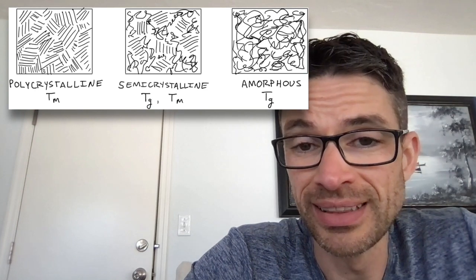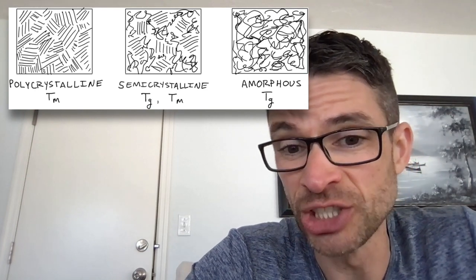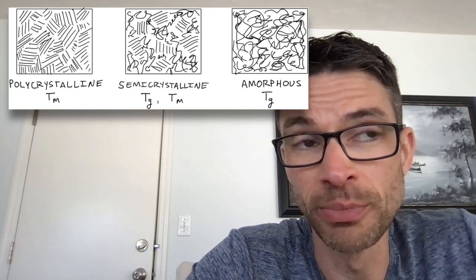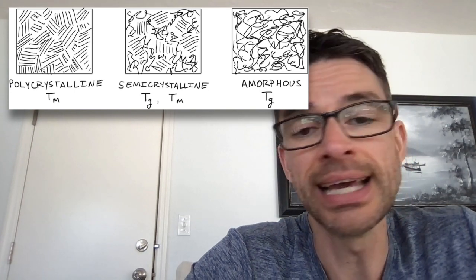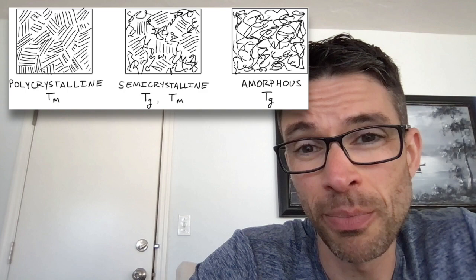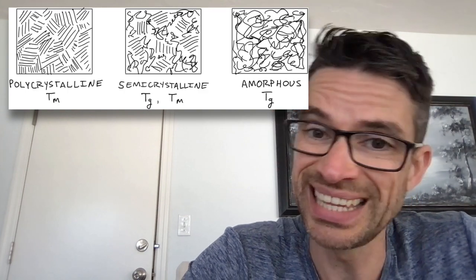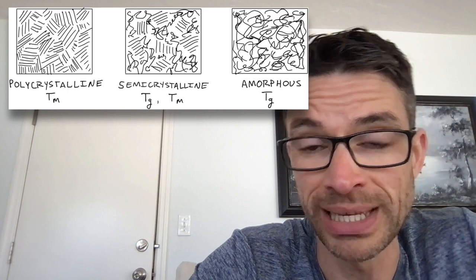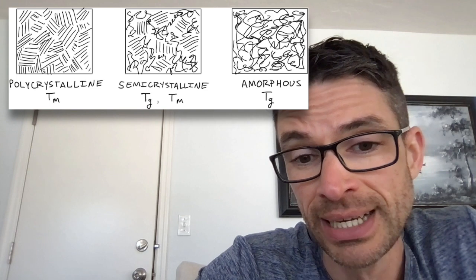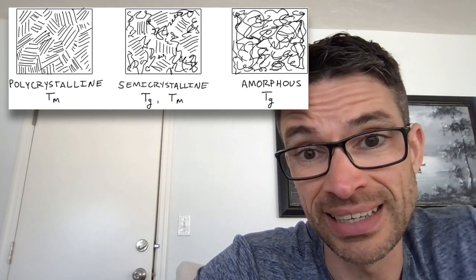The semi-crystalline sample thus has both a TM and a TG. Above the TG, the material becomes more elastic, and above the TM, the material is melt. If a material operates between the TG and the TM, chances are it's an elastomer — elastic polymer. There are many well-known examples of polymers that exist between a TG and a TM.